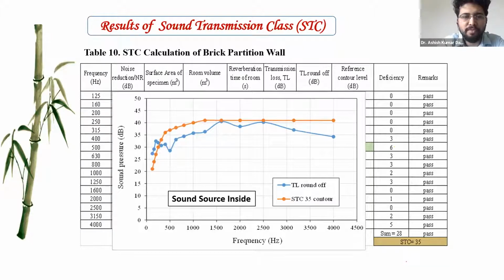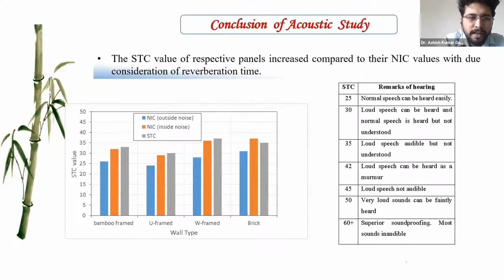And from this graph, you can see that the STC of the brick is coming out low compared to the W frame, that is the twin mesh system concrete panel, and it is quite comparable with the U framed and bamboo framed single mesh concrete panel system.